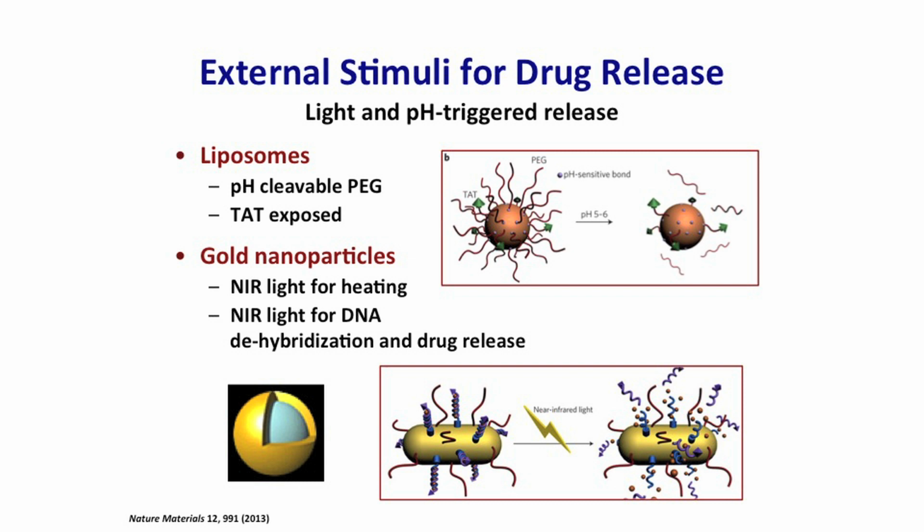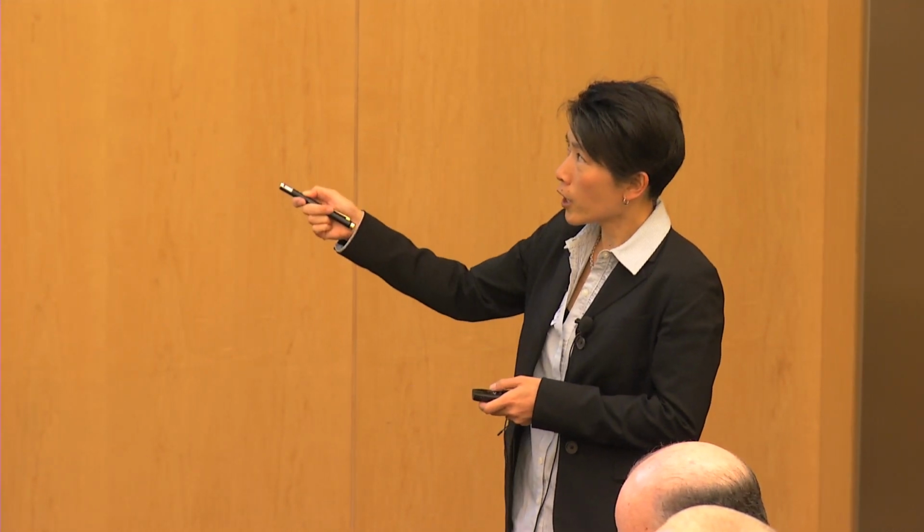And so the idea is you don't really have ligands on the outside or drugs that are doing anything, but this entity itself is heating. So you shine your infrared light on this particle, and this particle heats the local environment around it to induce cell death, and it seems to be working pretty well. The challenge, of course, is the time that you need to apply for heating is on the order of minutes. It's around 5 to 6 minutes of continuous irradiation, and it's fairly localized.